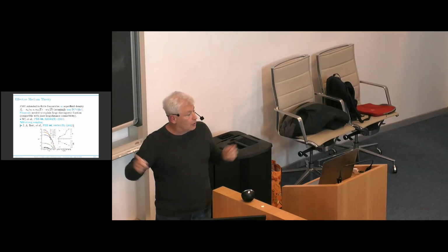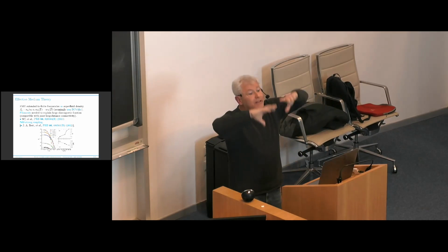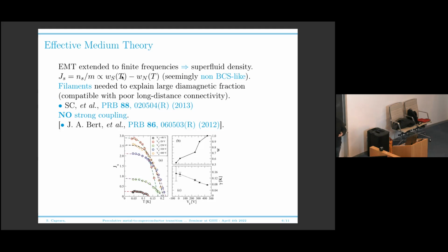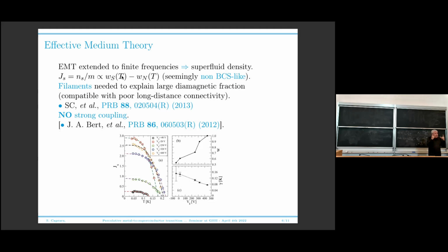And then you can ask yourself, what if now my superconductor percolates? And then the result is immediately this, that you can calculate now the reactive response of the entire random impedance network. Now you have an impedance network because you are at some finite frequency, and you can calculate the reactive response, and effective medium theory will give you that when the resistance of the cluster is zero, your response is purely inductive. So you can extract directly from the effective medium solution your superfluid fraction.